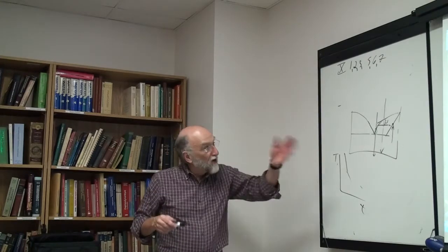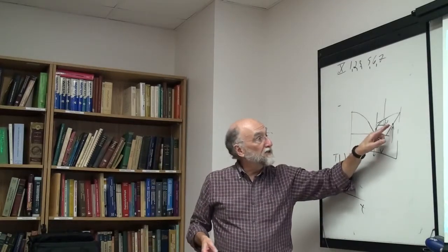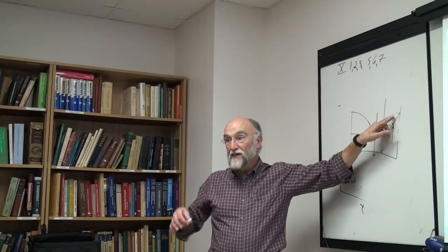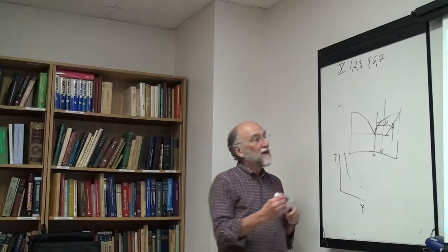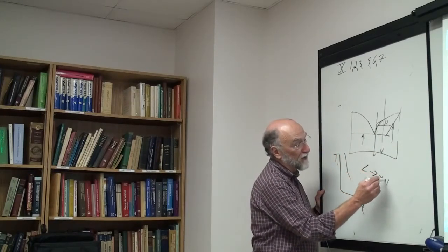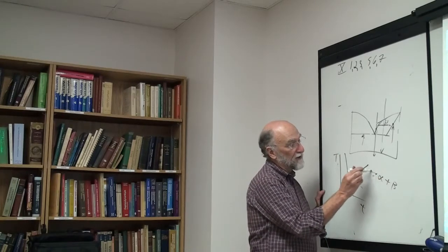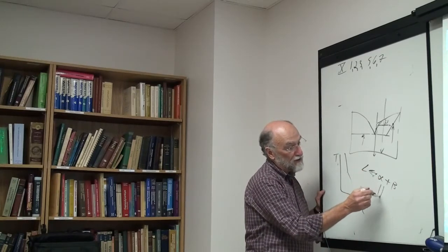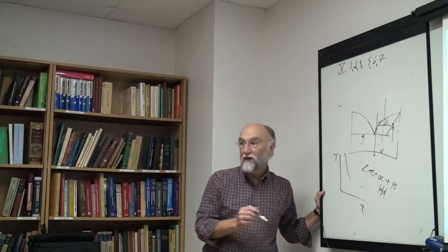You notice the temperature at which the solid starts to melt, and so you'll see a change in slope as you heat it. But then it's the same thing. As you heat to the liquidus, you're not going to see that, because that's just the end of the reaction. Seeing the beginning of the reaction is easier than seeing the end of the reaction. A heating curve to get a eutectic is sort of okay. The eutectic reaction is liquid gives you alpha plus beta. If you're going in the other direction, what is the alpha? It's only at the points of contact between the alpha and beta phases that you're going to get fusion.